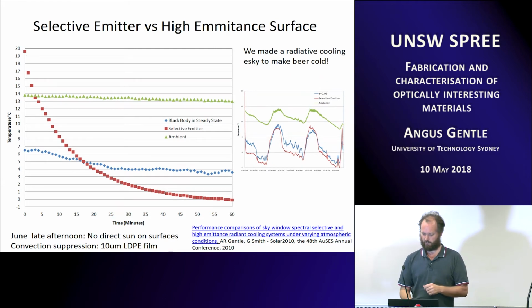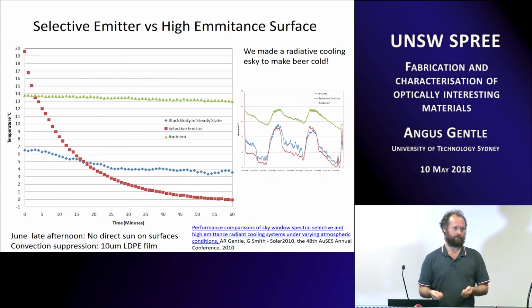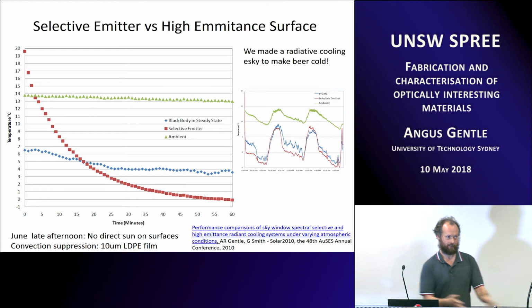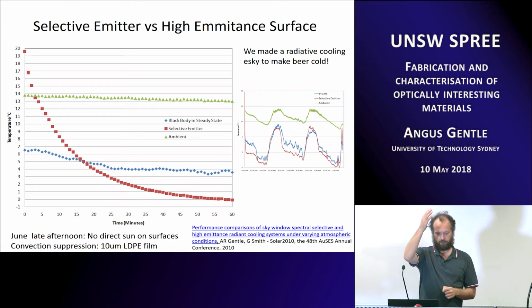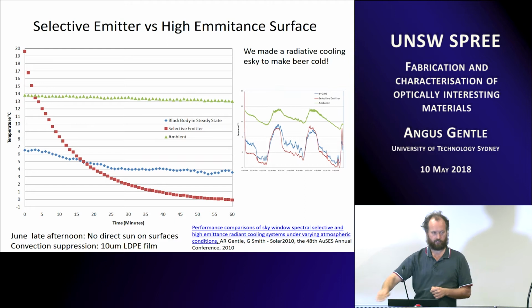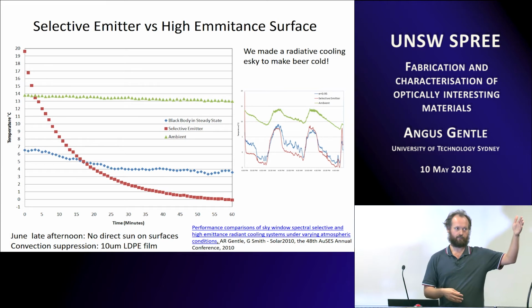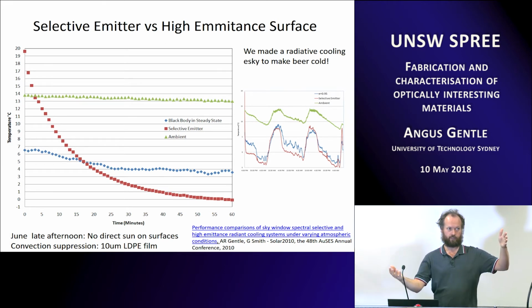This was done in, I think it was about June, so it was late afternoon, and that's why the temperatures are cool. You see that the selective emitter started off warmer than ambient because it came out of our lab, we walked outside, had it all plugged in, and turned it on straight away. Within the first hour, it had dropped from above ambient down to 0 degrees C, even though the ambient temperature was 14 degrees. So we're making ice straight away. This is set up not in direct sun, so it was shadowed because it's late afternoon in June. You can do it just in diffuse light, so you're still getting 50 to 100 watts per square metre of sunlight coming in, but we're still getting significantly sub-ambient.